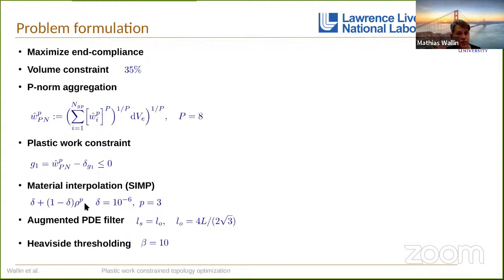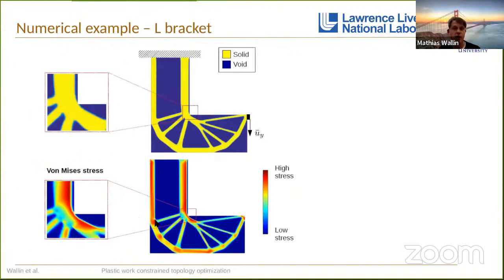Material interpolation turns out to be kind of critical. In this case, we use exactly the same SIMP exponent for both the yield stress and the elasticity. We haven't done that before. When we did energy maximization, we had the exponent for the yield stress slightly lower than for the elasticity. And we use this augmented filter that I just showed you, and some standard techniques, Heaviside thresholding with beta equal to 10 at the end state. So one well-known example, we have seen it today, is an L-beam. We load it with displacement control, and with a constraint on the plastic work.